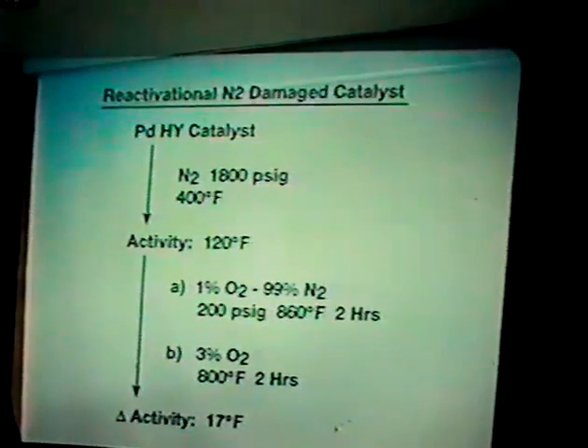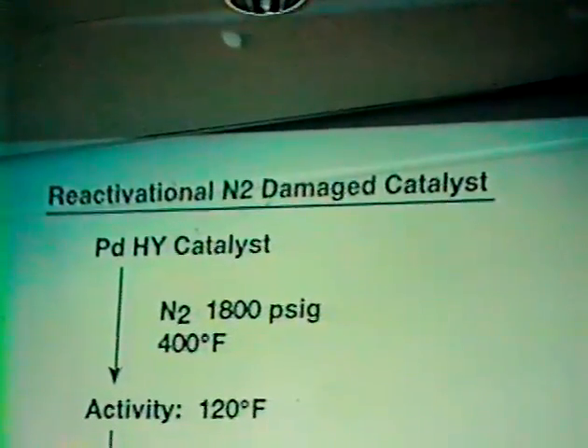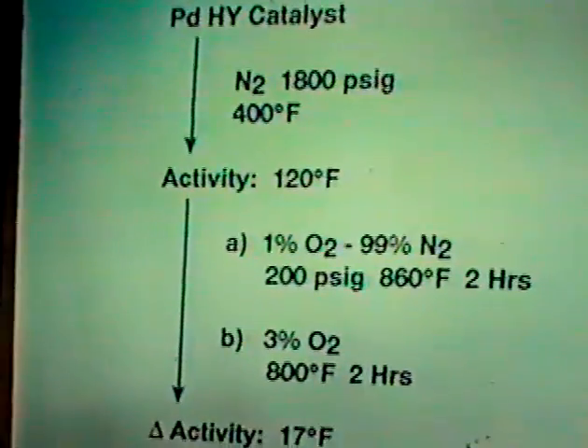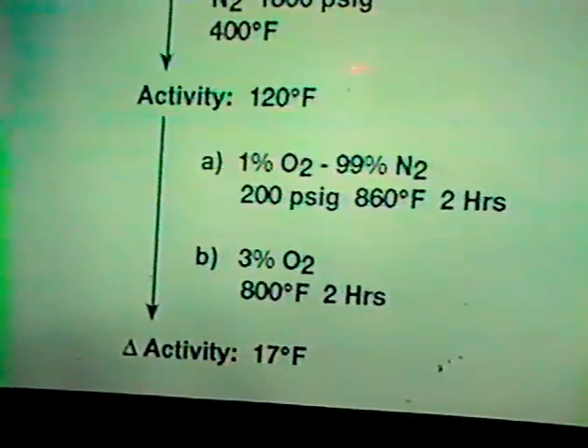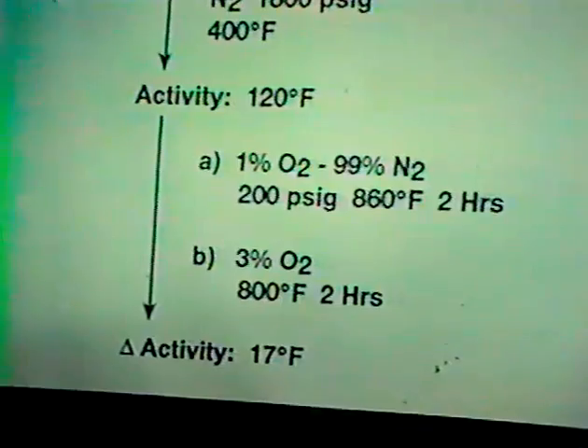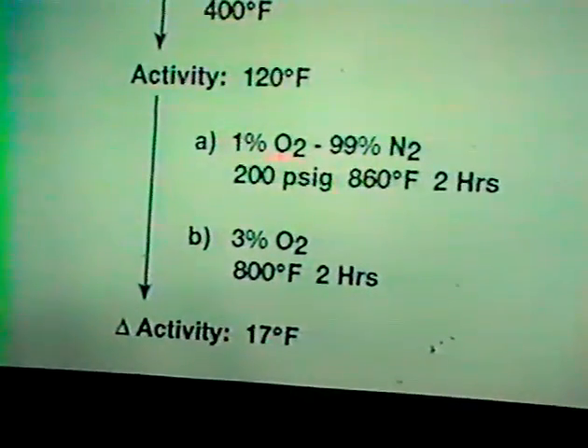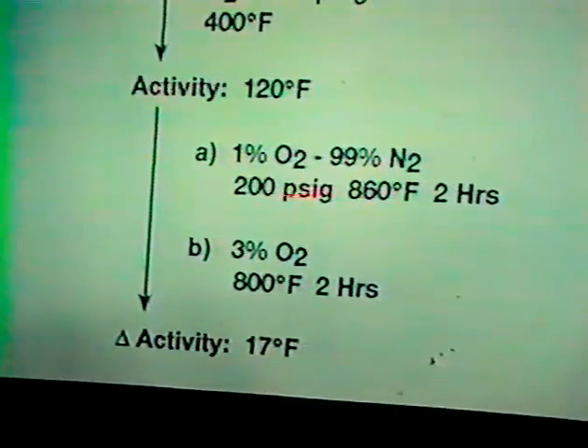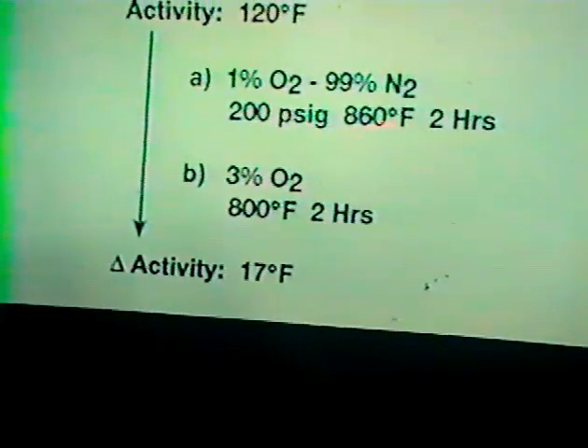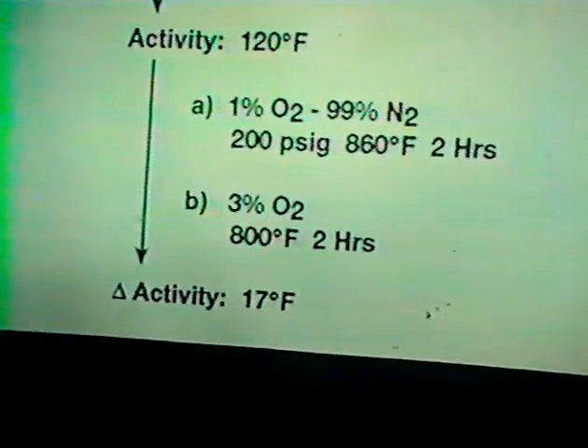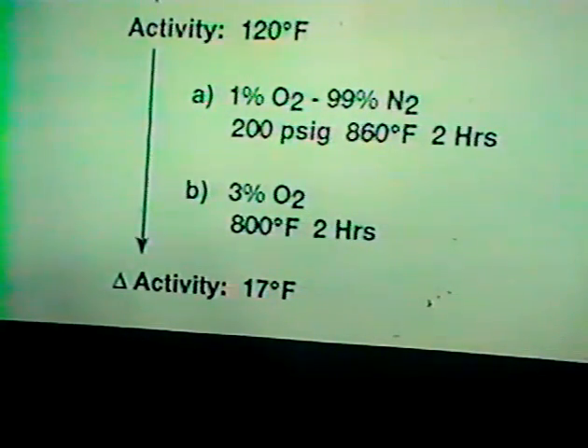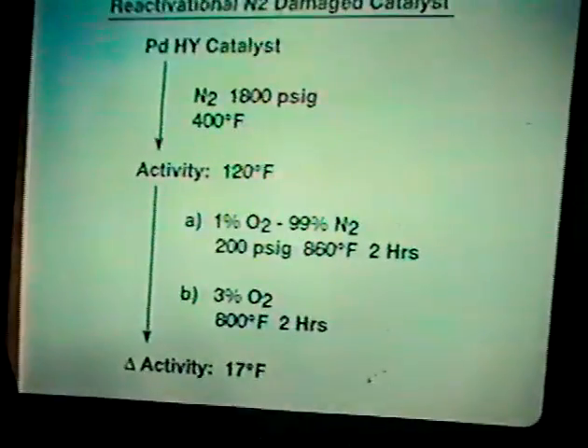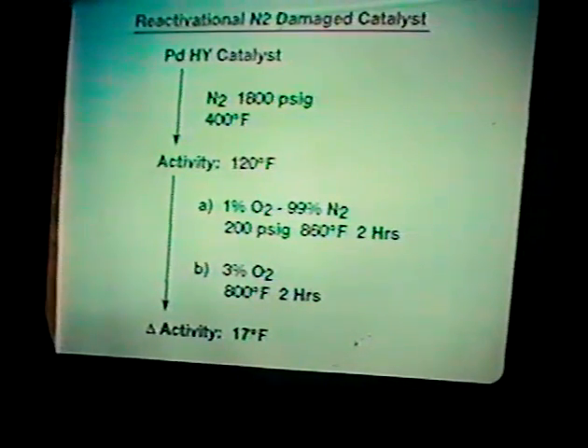What we have discovered, taking some of the data off there, if we take the palladium catalyst treated with nitrogen, at this time 1800 pounds pressure, 400 degrees F, it loses 120 degrees in activity. And then, when reduced with hydrogen and run in a test reactor, you can then take that same catalyst and retreat it with 1% oxygen, 200 pounds, 860 degrees F, which is around 460 degrees centigrade, 2 hours, followed by a further treatment. The catalyst reactivates to within 17 degrees of the original catalyst. What's happening here, we've no idea. So, some effect of the nitrogen must be moving around the palladium in this catalyst system, and whatever damage is done can be restored by a mild oxygen treatment.